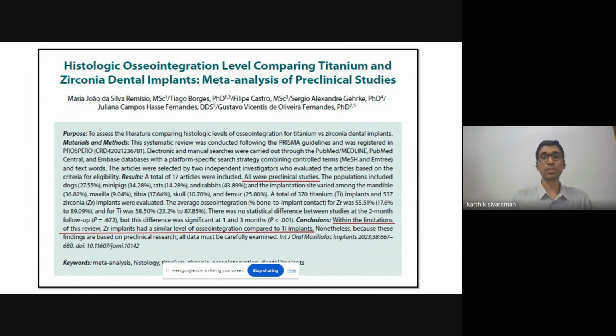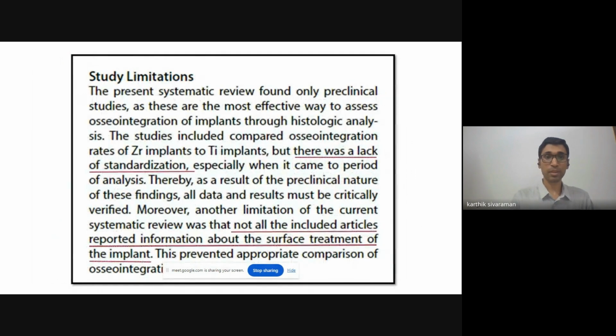So according to them, there was no difference between the level of osseointegration or bone implant contact observed for both the types. However, there was an important study limitation, and that is always something which we need to look out for when we are looking at the results of any study. There was a lack of standardization in terms of period, as well as the surface of the implants which were assessed. Many of the studies did not mention whether they were using a roughened surface or a smooth surface, or even to what level the roughening was done. So there was an ambiguity in that case. So that prevents an appropriate comparison of osseointegration and an appropriate result of what could be told.